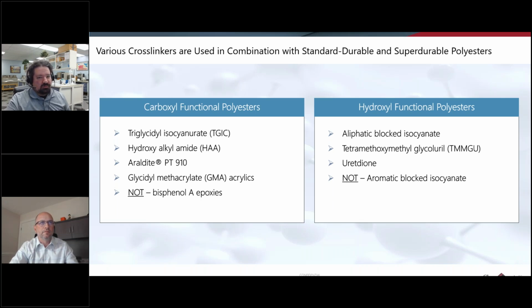And then again, polyester with an epoxy in it is not going to be weatherable. Hydroxyl functionality is typically going to be cured with an aliphatic blocked isocyanate. Those have a blocking mechanism that comes off when it hits a certain temperature. The key thing here is that they have to be aliphatic. There are aromatic versions of blocked isocyanates, but those are not weatherable. Obviously not going to be able to use those for architectural coatings.